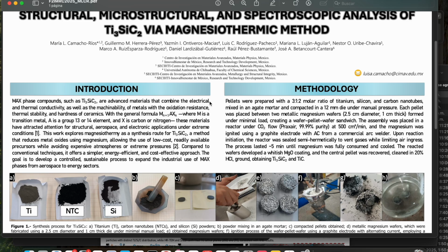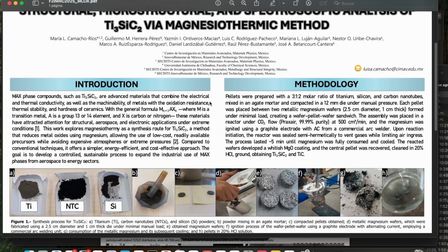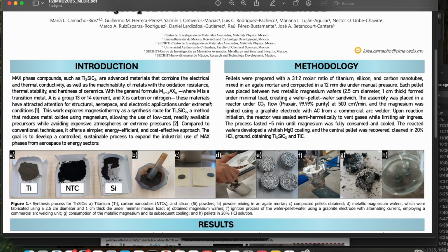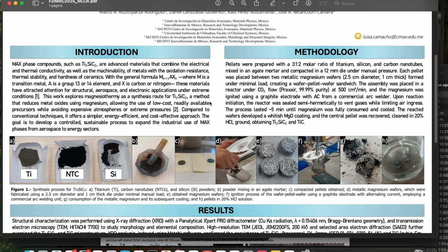We mixed titanium, silicon, and carbon nanotubes in a 3:1:2 molar ratio, compacted the blend into pellets, and sandwiched each pellet between two magnesium wafers that act as an in-situ reductant and heat source. The assembly was placed in a reactor with CO2 flow to moderate ignition and gas evolution.